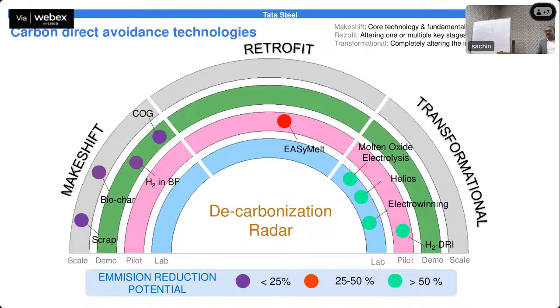But still, only 50%. So the point is, this is still on the left-hand side of the previous graph. It means direct avoidance of carbon. You can at best get around about 50%. But mostly, if you use existing technologies which are easier to use, easier to scale, you'll get 25-ish at best. When we put hydrogen in the blast furnace, we put 40%. You can go to 100% for the H2-DRI, but you still need carbon. You can do about 12–15% of replacement of the carbon.